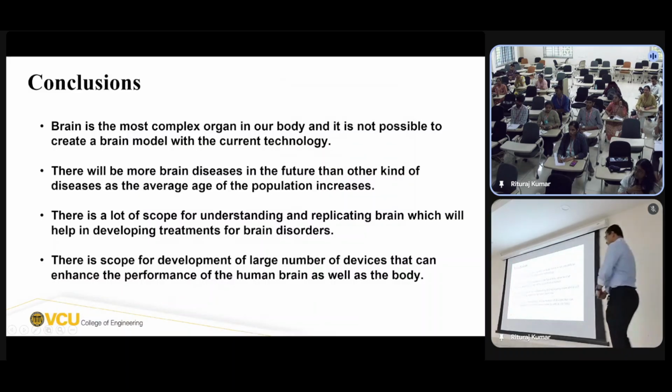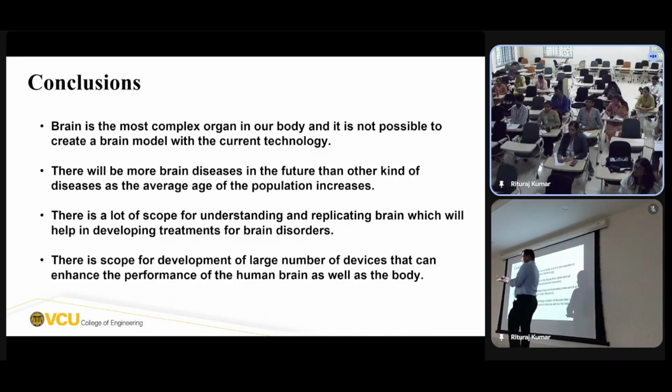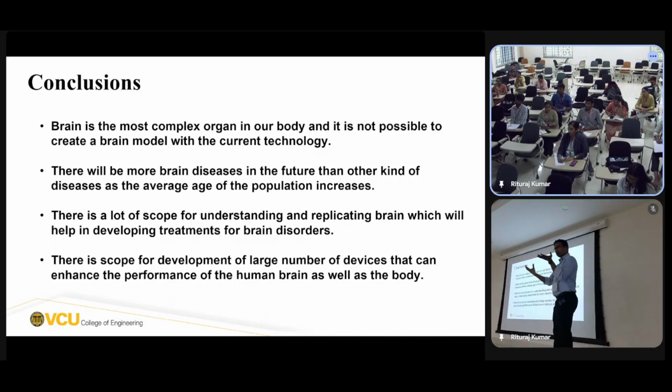So you got the idea, right? So there is a piezoelectric at the bottom. On top, you have a magnetostrictive material. Apply magnetic field, magnetostrictive material oscillates, that creates piezoelectric oscillations. If piezoelectric material oscillates, what happens? Generates a voltage, right? And that voltage can be used.